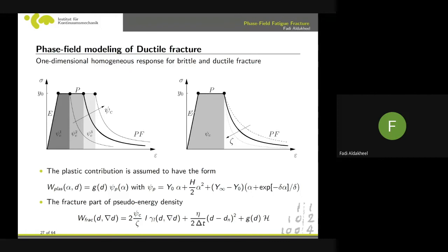So now I can apply the same method to fractures. I can introduce either a fracture without threshold, which I introduced before with the GC criteria, or now I introduce it with threshold. With the threshold, that means you have elasticity, for example, till some limit and then the fracture takes place. Or you have elasticity, then plasticity, and you have a zone which is undamaged, and then damage, with the same thinking as elasticity for the damage, right? So you also have an extended yield, if you want to think about it.